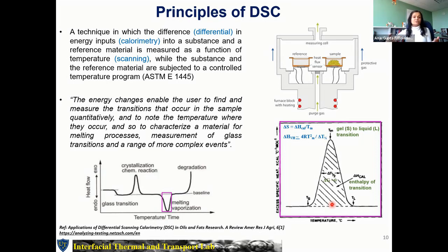So just by doing a simple DSC run, we can figure out what's happening in the lipid bilayer, how molecules are interacting. In this talk, I won't have the time to talk about our cooperative units or cooperativity analysis, but do know the location of the peak, the size of the peak, the shape of the peak gives us a lot more information other than just melting temperature.